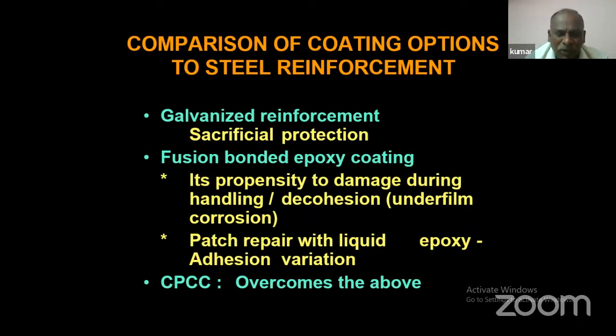Okay. Then what is the problem of fusion bonded epoxy coating? Number one, it is highly organic based. Our steel reinforcements are designed for the structure based on the bond. When fusion bonded epoxy coating is applied, the interface between coated steel and the concrete has only 85% of the bond of conventional reinforcement. If reinforcement bonding is 100%, it has only 85%. This is one of the disadvantages. Correspondingly, you have to increase the number of steels and so on.